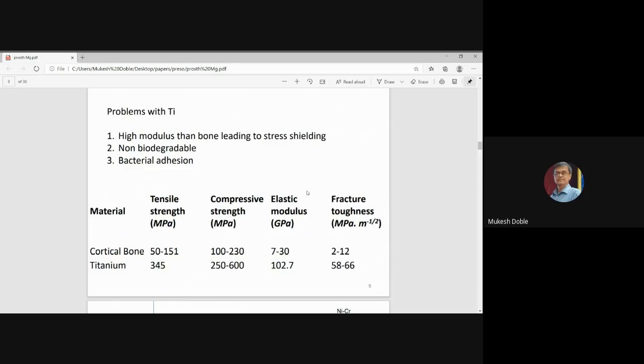to bring in metals whose tensile strength and elastic modulus are closer to the bone. Success has not yet been achieved, but people are looking at alloys, putting in aluminium, zinc, vanadium, so many different metals, so that these mechanical properties could be brought down. Ultimately, if you have a metal with properties similar to the bone, then the stress shielding issues are not there. If somebody has a titanium rod placed in the leg, and he or she walks, most of the load will be transmitted through the titanium. The load through the bone is less, so it slowly does not function properly. It loses its strength, becomes more porous, and those portions get weakened. That's called stress shielding.